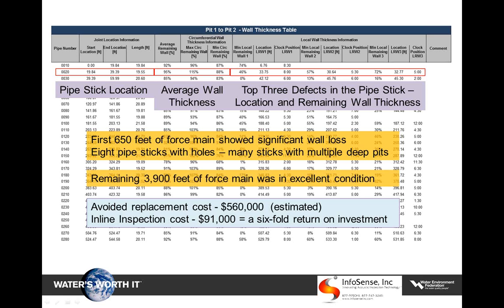Of more importance to the client, the remaining 3,900 feet of the force main, as it got away from the marine area, was in excellent condition. So if this data could be believed, they felt very confident they could avoid replacing that 3,900 feet of pipe, saving a little over $500,000. And if so, then the cost of the inspection would have a 6-fold return on investment for them. They were very excited about this, but they wanted to verify it.